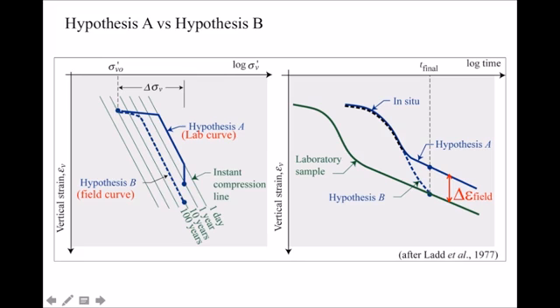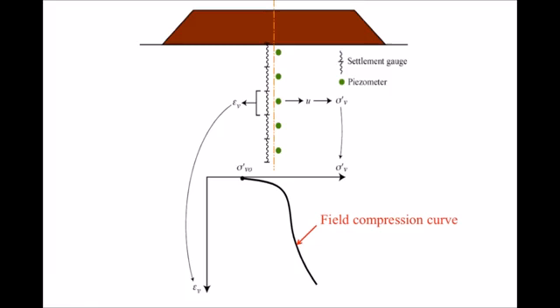So we have examined this aspect by examining the effective stress strain curves in situ, so under embankment. If we have deep settlement gauges, as for example here, we can define the evolution of strain and strain rate with time. But also if we have the pore pressure, we can define the vertical effective stress and then get the field compression curve, which is the truth. The nature is saying that's a compression curve.